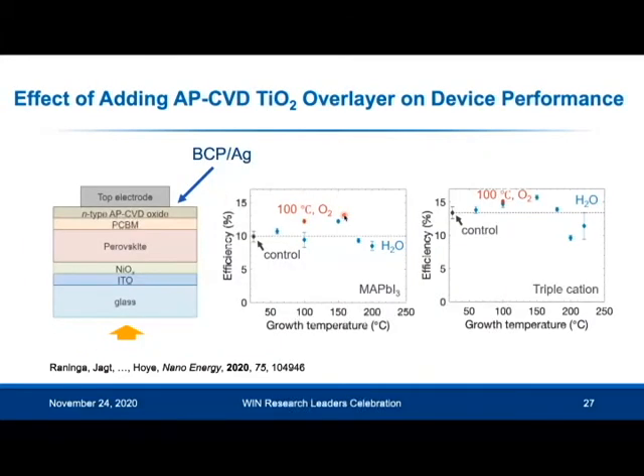So now that we know that we could avoid degrading both the bulk and the surface when we're growing 7 nanometers of TiO2 by APCVD, even under strong conditions, we now want to see what the impact is on the device performance. So we looked at both the methylammonium lead iodide and the triple cation perovskite devices, and the black diamonds represent the control efficiencies, which is where we don't have any oxide between the PCBM and the top electrodes. The red diamonds represent devices with TiO2 grown under mild conditions, and the blue diamonds represent devices with TiO2 grown under strong conditions.